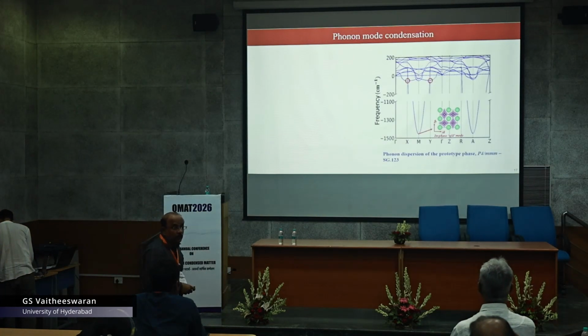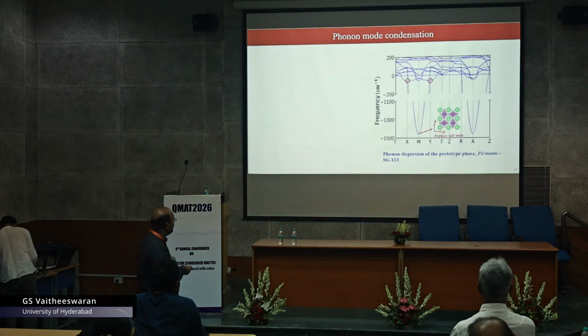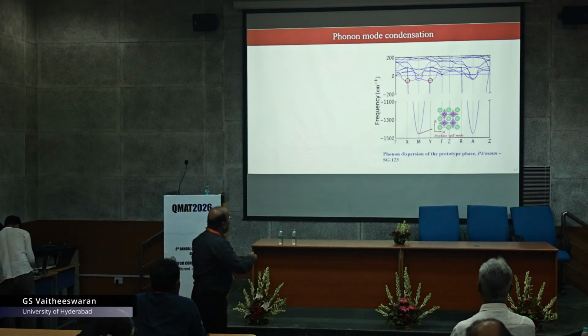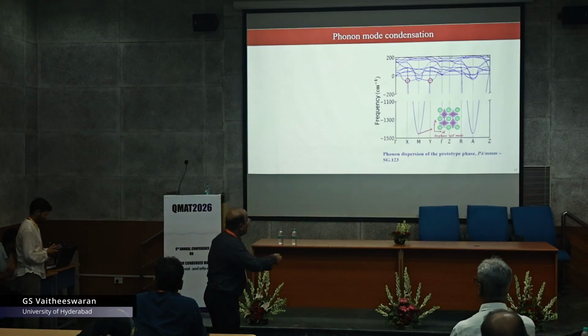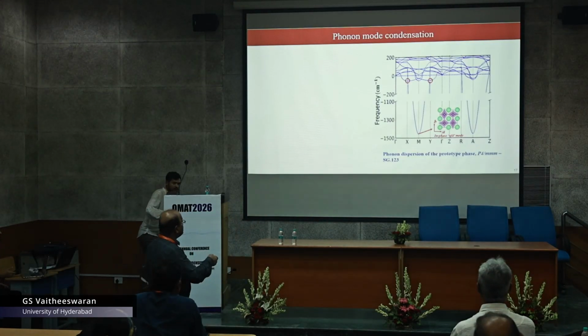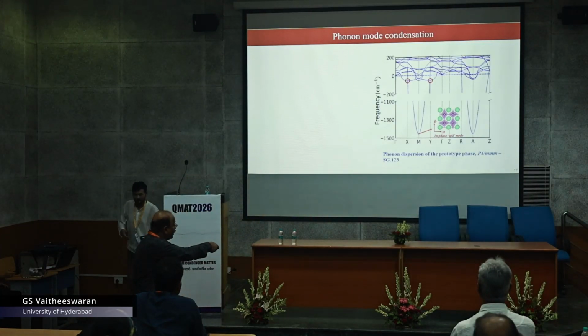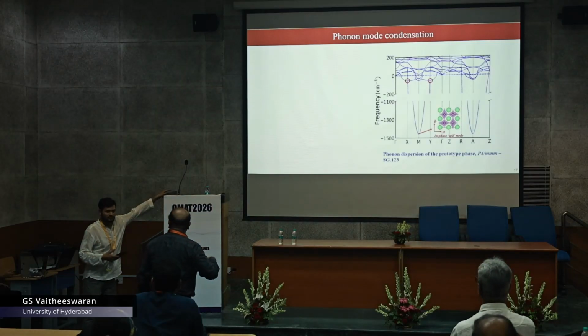Then we computed the phonons. And surprisingly, we got a large imaginary phonon mode at the M point as well as at the A point. So this is with this particular space group P4/mmm, which is 123.